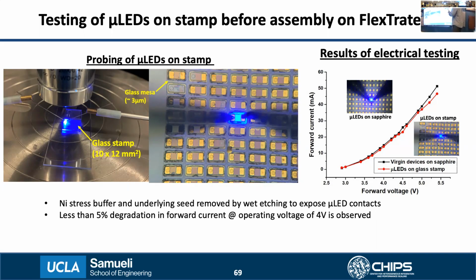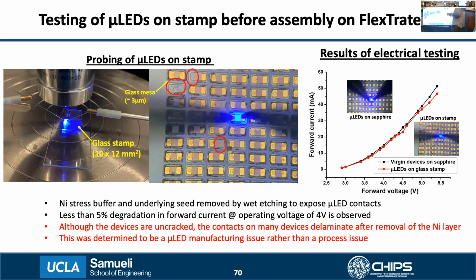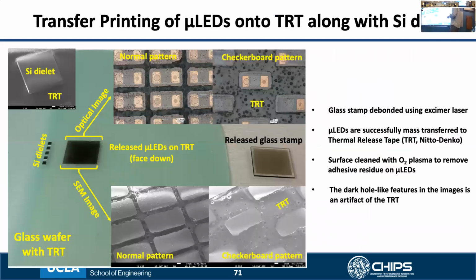observed. However, we did face a problem while doing this mass transfer process, which is that if you can notice, the contacts in many of these locations had actually delaminated once we removed the nickel. And what we found later was that this was actually due to a micro LED manufacturing issue rather than a process issue itself. So I'll talk about this in the remaining slides of this presentation.